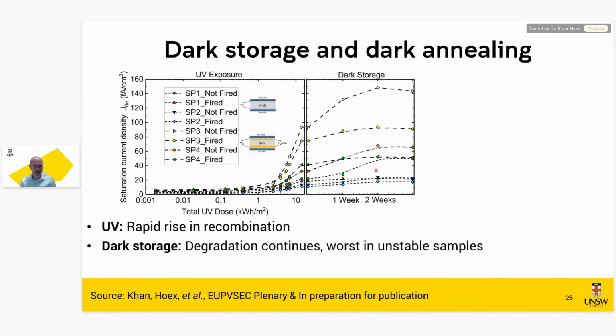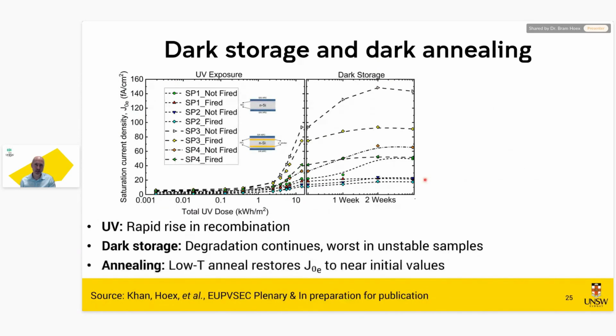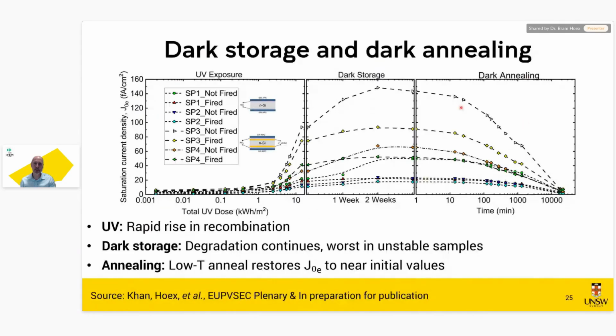And we see that there's a bit of scattering in the samples, so we see that the sensitivity is not uniform, but the worst performing samples, they really see, particularly this one, a rapid increase in degradation. And then in dark annealing, which is done at 85 degrees, we see that we can basically get it back to the normal value. So 85 degrees is, of course, higher than you would typically see in the field, but it's again an important piece of the puzzle. What is causing this degradation?